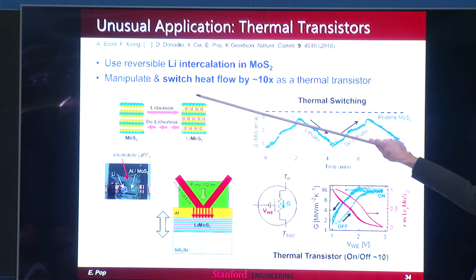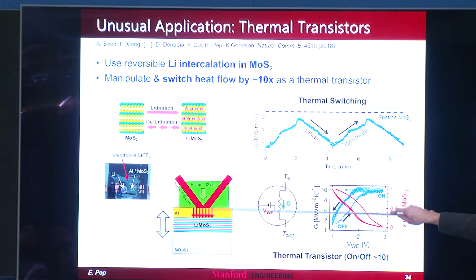Again, this is heat flowing in the cross-plane direction, and what's cool is that this thermal transistor has an on-off ratio of about 10. And if you work with graphene, you know that's a good on-off ratio. And so for a thermal transistor, of course, we'd always want it to be higher. Turns out the higher the better for thermal transistors too. But 10 is actually pretty significant for modulating heat.